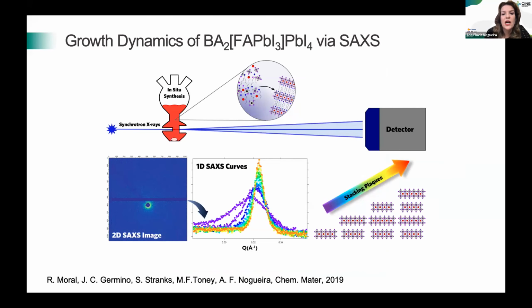So as you can see here, this is the data that you can get from the SAXS, a 2D image. Of course, you have to treat this in order to get the 1D data here, where we have intensity as a function of Q. Q is related to theta. That's something interesting from these in situ experiments when you go to the synchrotron, because you cannot do it in your lab. You have to go to the synchrotron because we have this fast detector here that allows us very, very fast acquisition of the data. So we can see here when you plot with time, you see the growth of this very nice peak at about 0.33. This is the 0 0 diffraction peak, from the stacking of these perovskite layers here.